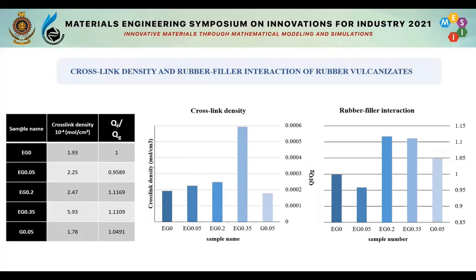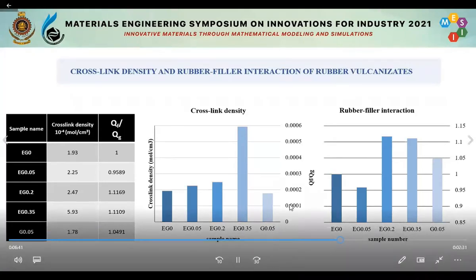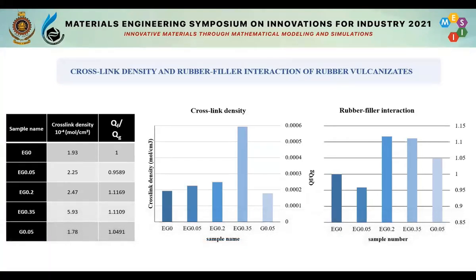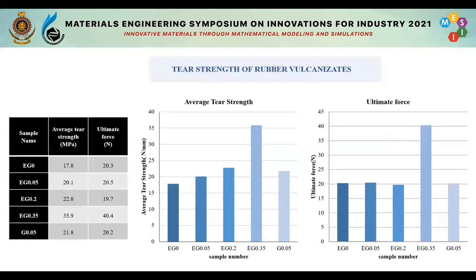So when we look at the chart, we can see that if we use the same amount of exfoliated graphite and same amount of graphite in rubber latex vulcanizate, rubber filler interaction has been increased if the graphite is exfoliated. And it can be identified that there is a limit to the amount of exfoliated graphite that can be used in the rubber matrix, as after 0.2% of exfoliated graphite being used, it can be seen that the rubber filler interaction has been reduced. Analyzing the test results of tear strength test for rubber vulcanizates.